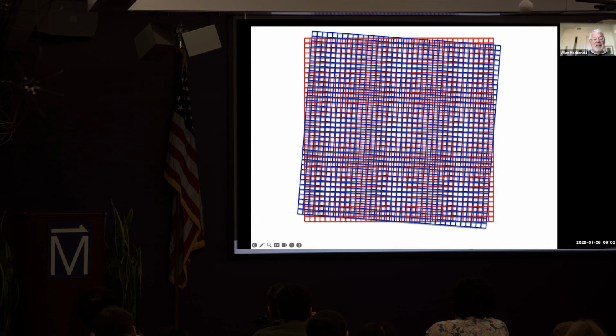In this case, if you tilt them, you can see again that there's a periodic pattern, and you can characterize that periodic pattern. In this case, I've rotated the blue crystal relative to the red one, and you can see that locally, what you do when you rotate one of the layers is you just change the stacking between the layers. All of the atoms in some little region, if you can see my cursor, in this region, in the white regions here, the red atoms, lattice are right on top of, right below the blue ones. And as you move through the crystal, you're basically just slowly moving the blue lattice rigidly relative to the red one.